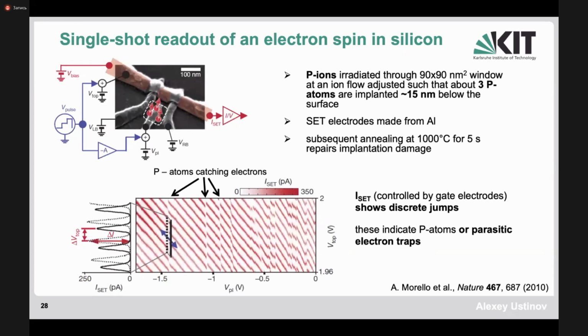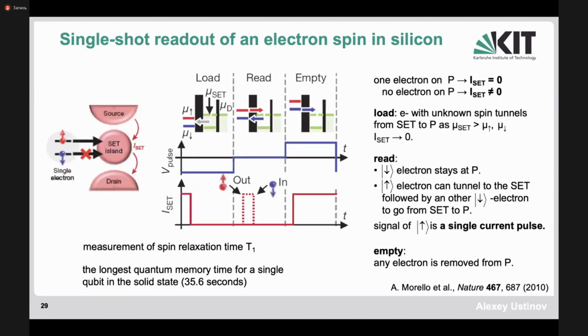So basically, these stripes which are observed here, this increases the currents, which are changed proportionally to the top voltage and the plunger gate. They show that the single electron transistor works and can be used to manipulate small charges nearby. And then it turns out that they have seen a small shift of the line of the blockade, as you see here around this blue arrow. And that's where they were doing the experiment shown in the next